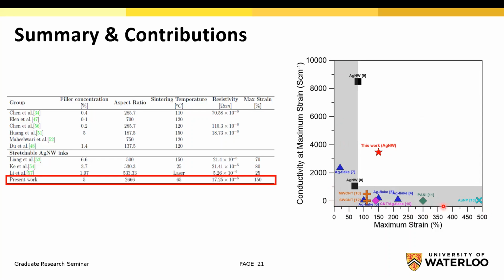So they are usually stuck in this region, but we can see that our work, silver nanowire ink with optimization, is a breakthrough in both conductivity and maximum strain, and we can tolerate a really high maximum strain with a really high conductivity.